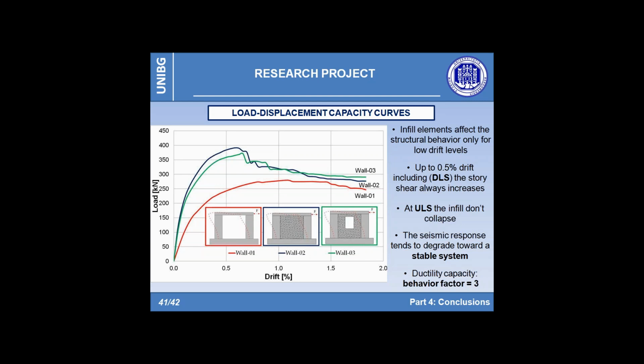Concerning the behavior at the damage limit state, it is also interesting to note that for cycles at 0.5% drift, no significant cracks on infill panels have been observed. Up to 0.5% drift included, the story shear values have always been increasing, and the first relevant structural damage affecting the infill has been recorded only during the cycles at 1% drift.